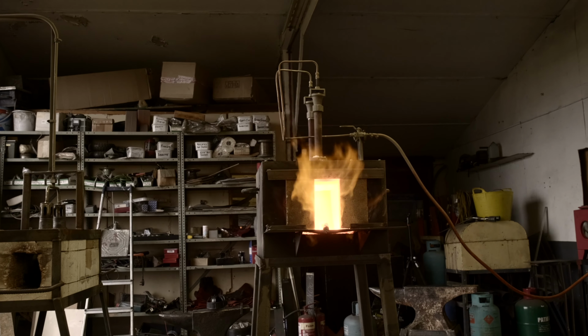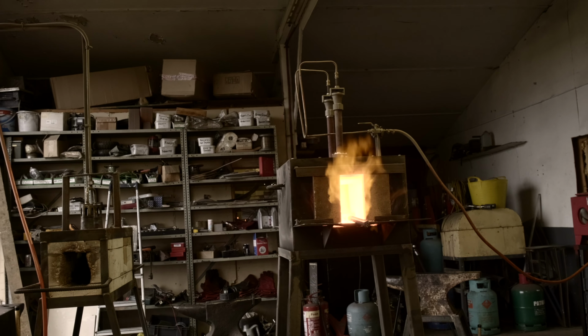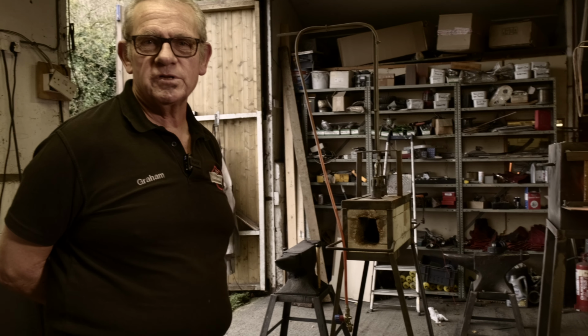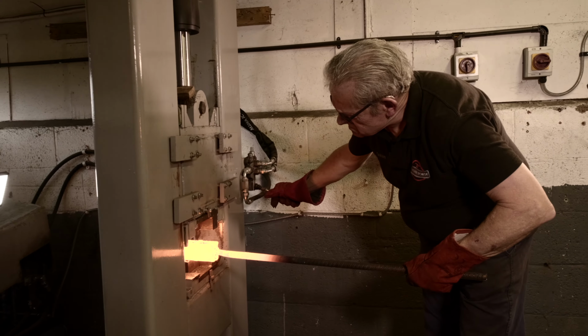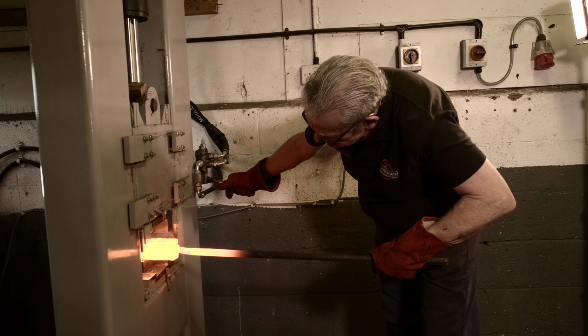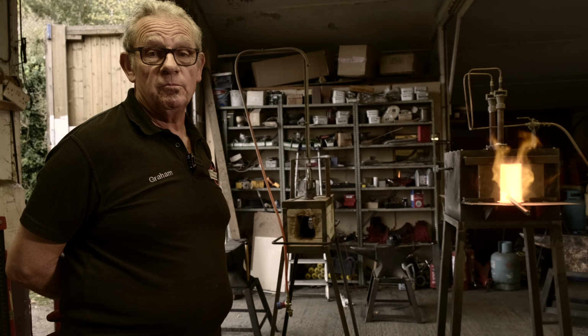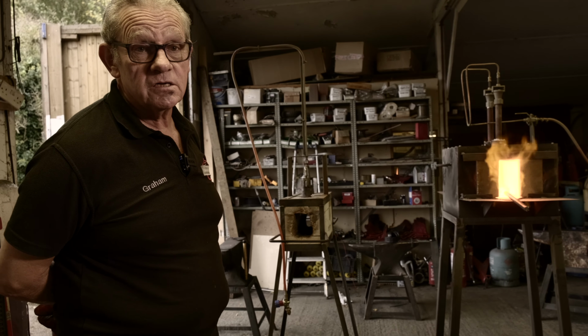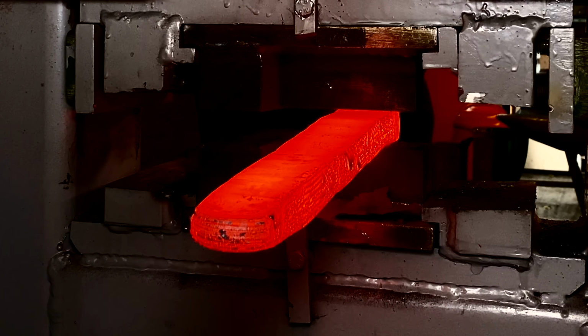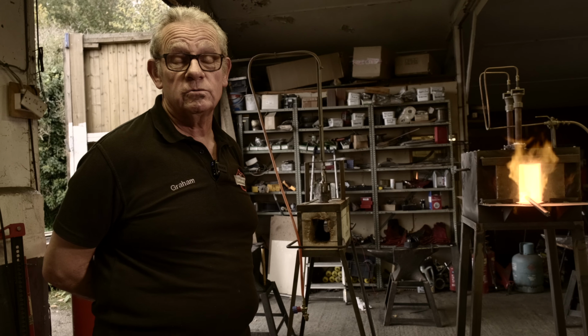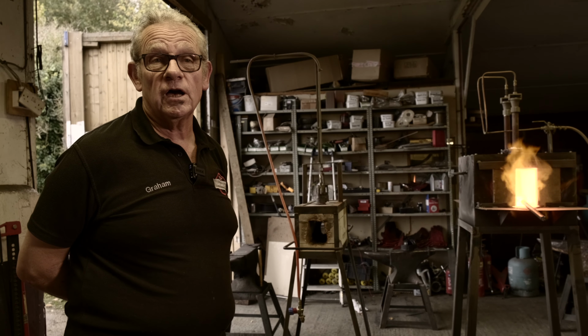Now, during the early stages of forging down, while that block is still big and heavy, it takes quite a long time to come back up to temperature. But then when we get it into the press, because it's a big block, it doesn't lose the heat quite so quickly, so we get a bit more forging time. As the billet gets longer and thinner, it heats up quicker, but it also cools down quicker when it goes into the press.